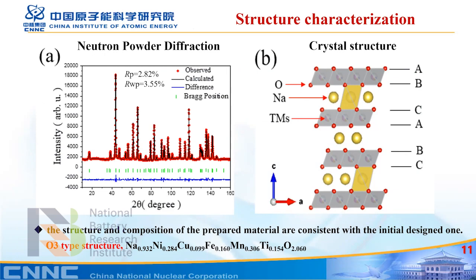And you can also find that at high angle is much better data and a very good resolution compared with X-ray. That is very sensitive to light elements like oxygen and sodium. And it also can distinguish near neighbors like the transition metals, since we have nickel, iron, titanium, manganese and copper. They also have a very high Q range, so the high angle resolution is very good.